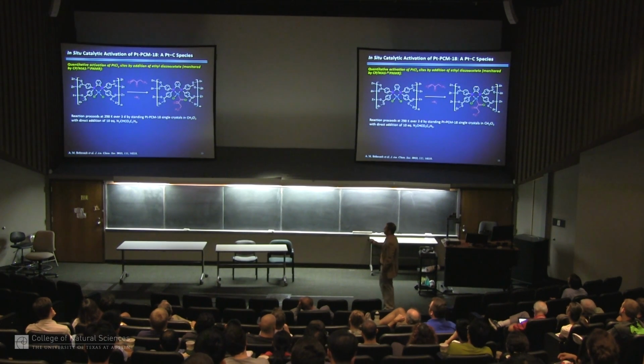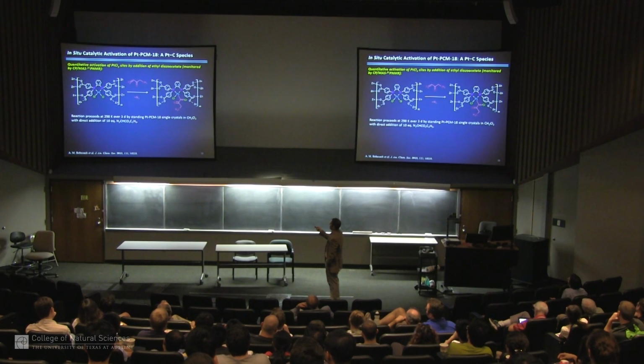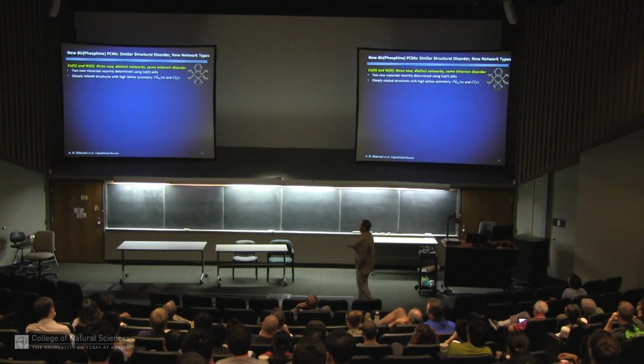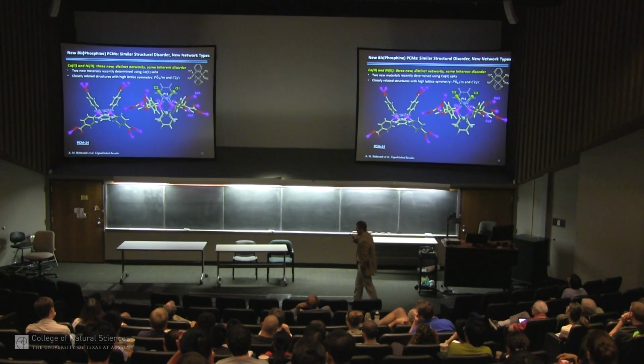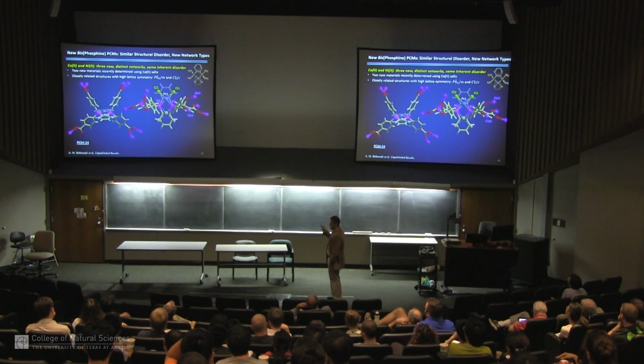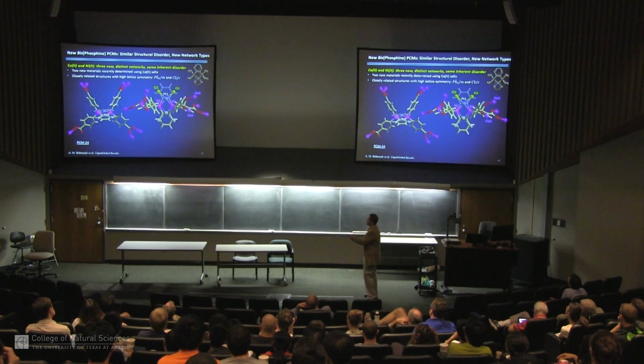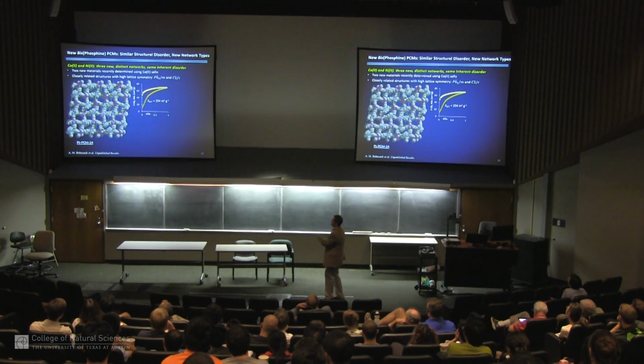Alicia also did some basic catalytic studies to show that these sites within the pores can be activated, and we can make these chiral intermediates by doing addition chemistry and making aryl metal carbon bonds. And the good news is, although I won't spend much time on these couple of slides, this is now a universal building block. Once you've done the chemistry to make the precursor, react with a different metal, in this case cobalt, we can make a different framework. Why is that useful? Because we can get access to different shaped pores.